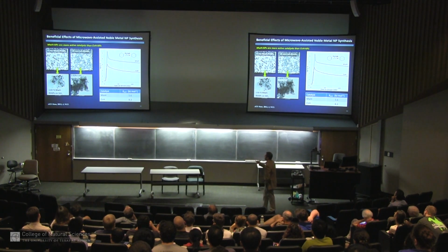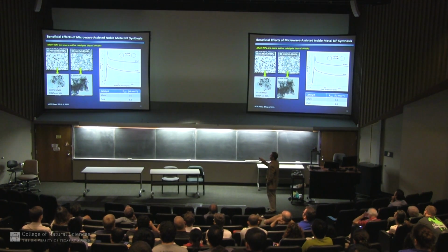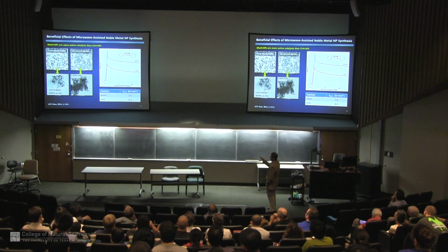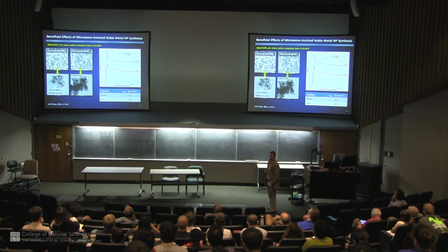And we found out early on that when you normalize everything and you look at hydrogenations of alkenes, which is, as I said, a very important basic reaction, you see that the microwave prepared particles are about twice as active as conventionally prepared particles. That's because the surfaces are cleaner, they're more crystalline, and you just get better turnovers. And you can see this played out in the activation energies on the surfaces.